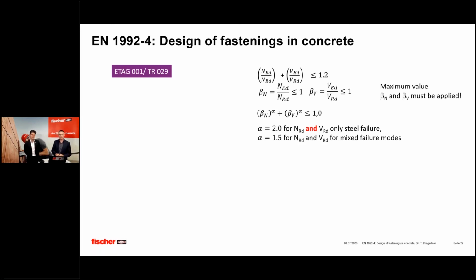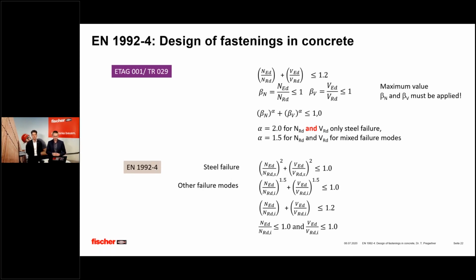Interaction you always show with a combined design proof where you take the ratio between action and resistance, which are called here beta N and beta V. And in the old guidelines, you always had to take the maximum utilization degrees independent of the failure mode. So what happened is you usually mixed in this interaction equation steel failure with the concrete related failure mode, which is conservative, but in some cases too conservative. So there EN 1992-4 improved it. And in EN 1992-4, you always have to do two different design proofs for interaction, which is always one for steel failure with the quadratic interaction equation, and then an additional one for the other failure modes.